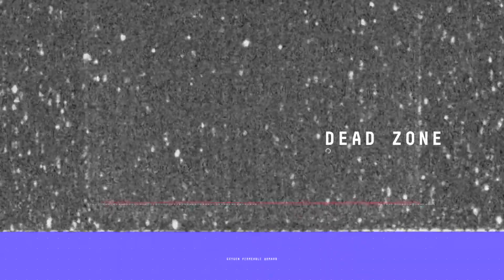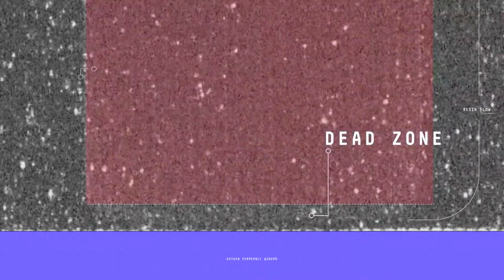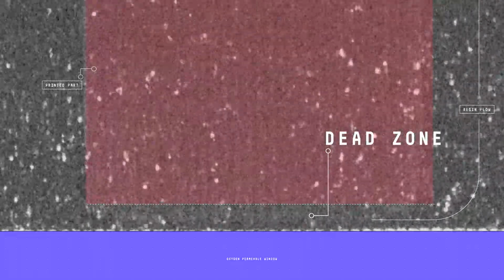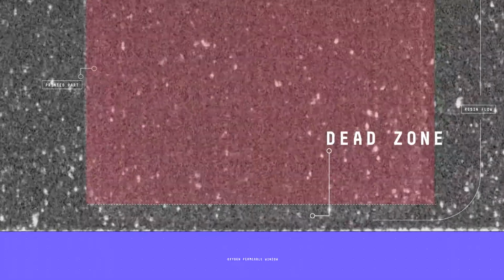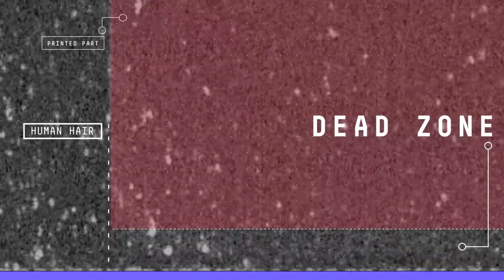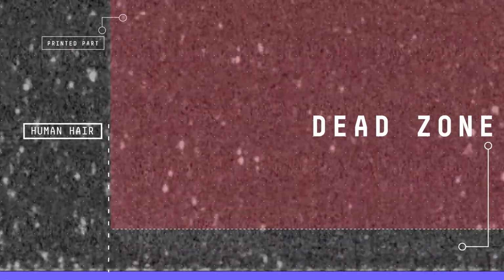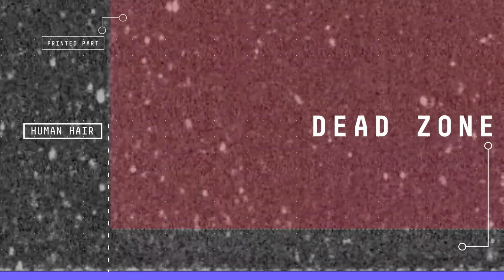What does this look like in real life? This is called an OCT measurement. It's actually, imagine sonar with light, and you can see the dead zone right at the surface of that window. That dead zone is roughly 60 to 100 microns, depending on the material that we're using. You can see the resin flowing through the gap, and this is what it actually looks like. So this part is about 2 millimeters in diameter, and it's printing at about 200 millimeters an hour. So that's a real-time image or video, and that is what we do.